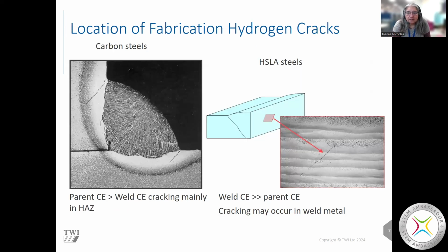And then another couple of pictures of where it can happen. Again, the weld toes, those are those corners where the weld metal meets the original parent steel, or in the root, that's in the bottom corner, or under bead cracking. And we've got this kind of abbreviation CE. CE is a compositional parameter called carbon equivalent, and I will be talking about that a little bit more later.